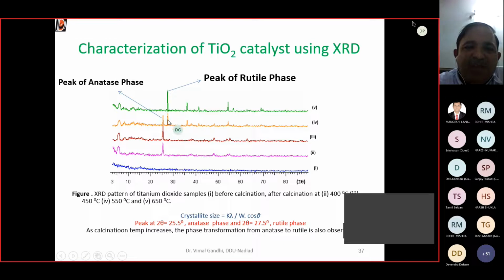peak. And then at higher temperature, 550, the anatase phase peak has decreased and another peak has increased. So this peak at around 27.5 degree 2 theta value is for the rutile phase. And finally at 650, the anatase phase disappears and you have only rutile phase.